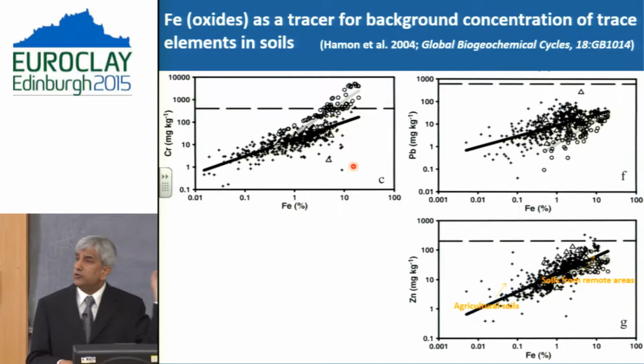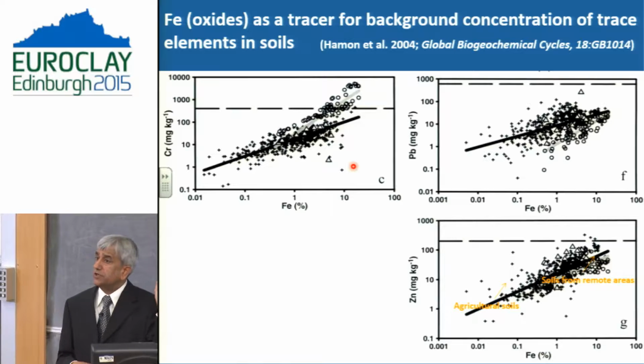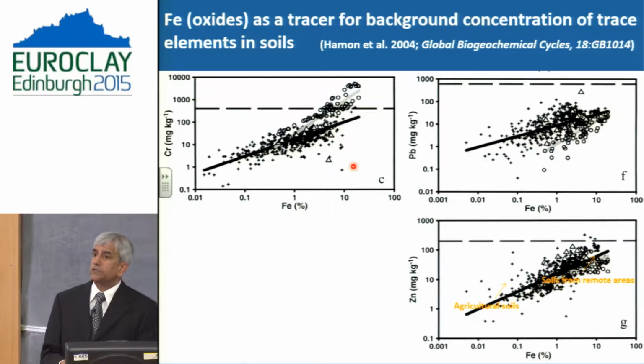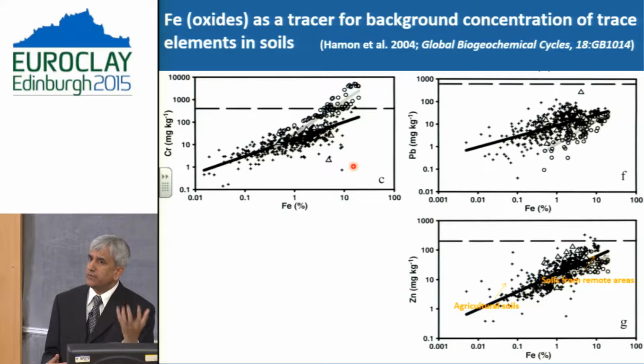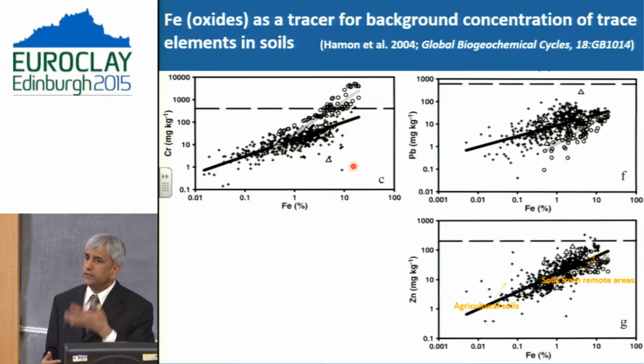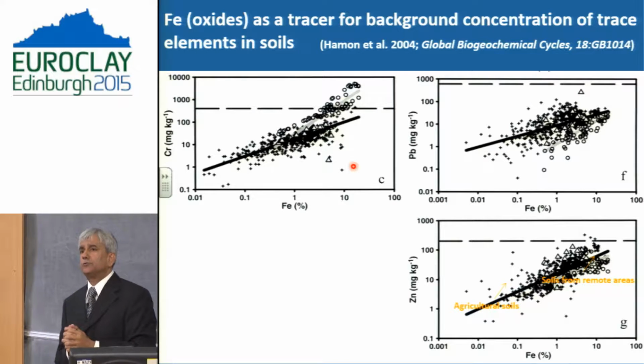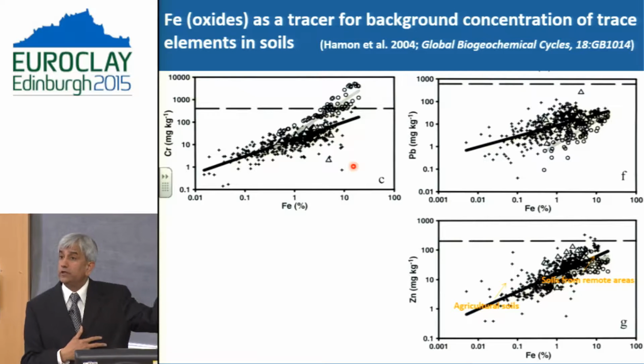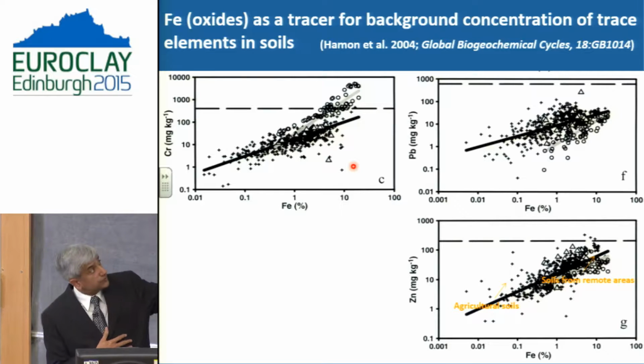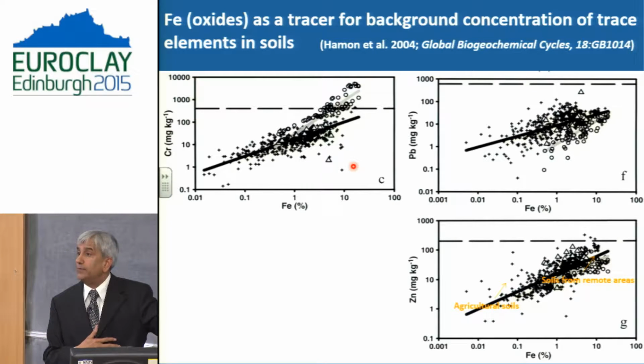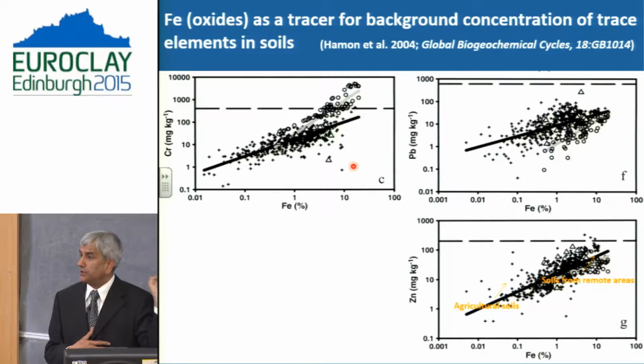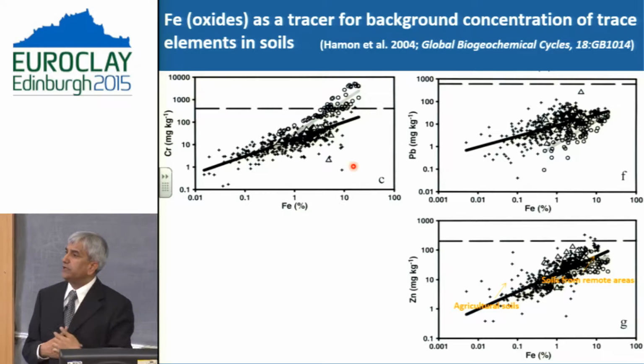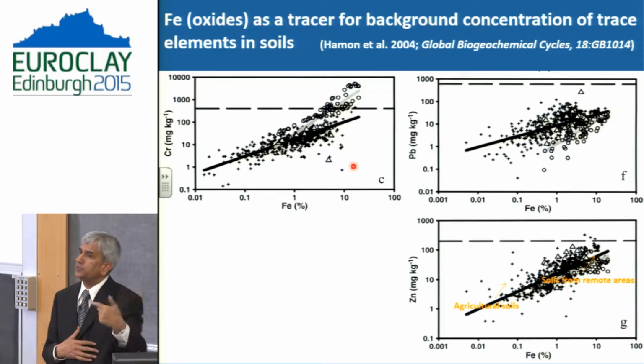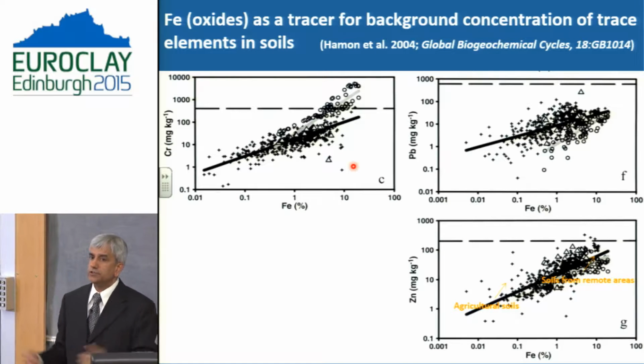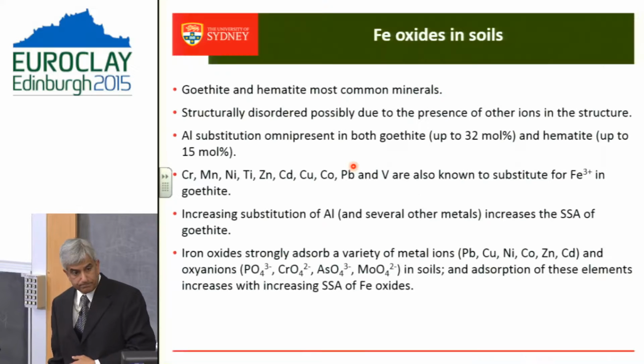So there you can see a clear application of those processes we have discussed, where either these elements are structurally incorporated in the structure of goethite or hematite, or they are adsorbed on the surfaces. But as a net result of those two processes, these elements are strongly associated with iron, and therefore we can use iron concentrations to predict the background concentrations in this system very broadly.